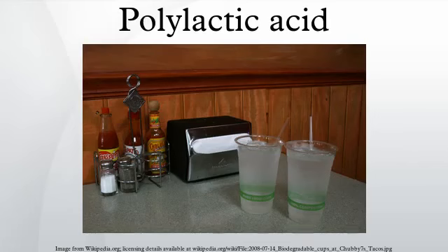PLA is also used as a feedstock material in 3D printers. The properties enable PLA-printed solids to be encased in plaster-like molding materials, then burned out in a furnace, so that the resulting void can be filled with molten metal. This is known as lost PLA casting, a type of investment casting.